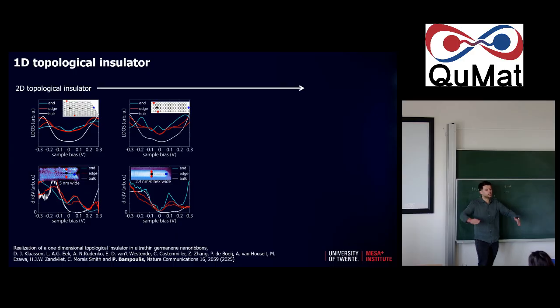You also get a peak at this location, indicating a 0D state emerging there. If you do now the same with the experiment, you see something similar. You see that the end of the nanoribbon lights up, which has a stronger peak compared to the edges.